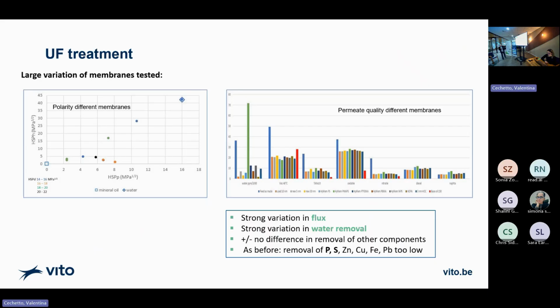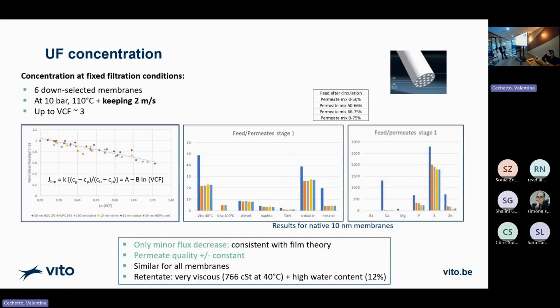Okay, what you see there is again the permeate quality of the different membranes, and actually there is not a lot of difference. And I can put many more membranes. There is not a lot of difference. Only the flux and the water removal is changing. Also, when you look at the metals, it's exactly the same picture. So from this, we selected membranes that have a good combination of high flux and a good water removal, so that we don't need any pre-treatment in the system.